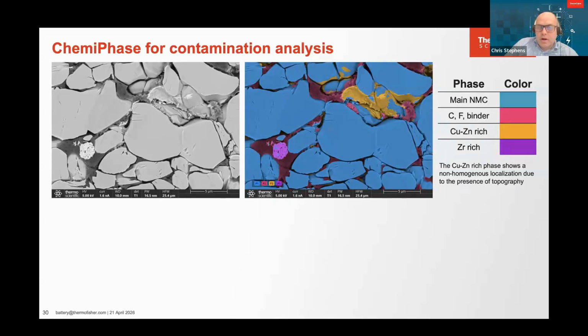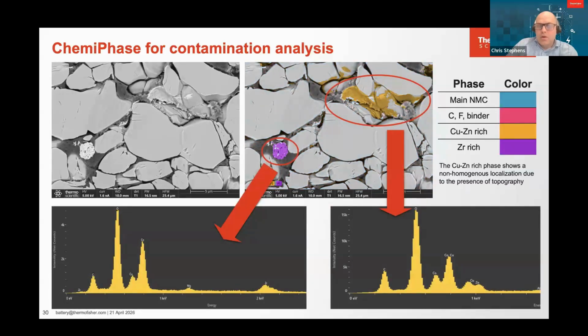And why this looks quite good, just click forward, is you'll see that in all cases, you're going to have quite a big background of the matrix itself. So this is the nickel, the manganese, the cobalt are going to be present in all of them. But in one, you have a copper zinc rich phase. The other is a zirconium phase. Just looking at the image itself, it would be very difficult to identify these. But in terms of the automated routine, it becomes really clear and obvious that these are different regions that you want to identify. So this is how we'd look at it in a screening.